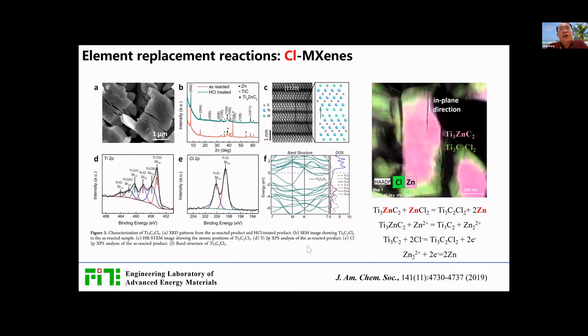And I think it was by accident that we changed the molten salt system, and used purely zinc chloride as a melt. And we found that there is an evolution from the zinc ternary MAX phase into the chloride terminated MXenes. So it can be a very green chemistry approach to make MXenes. Here we use the STEM technique to clearly see that all the terminations have been transferred into chloride groups.